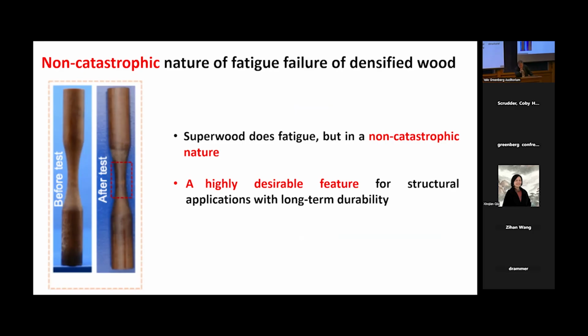By really carefully looking at the cross section, you start to see, oh, these are the cracks. Then we did the CT scanning to reveal that actually the cracking occurred across three quarters of the cross section, but not the whole cross section, and that's why it's non-catastrophic.